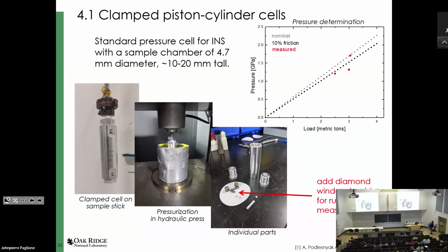But when we measured it with ruby, the first pressure point was spot on, but the second one was a lot lower. We realized it wasn't clamped sufficiently, even though we thought we were at the nominal pressure. When we clamped it again, we got to a lot higher pressure. These are caveats to be aware of, and it was really useful to have this offline pressure capability, because once you put it on the neutron beam line and you've already used 2 or 3 days of beam time just to realize your pressure was not correct, that can be non-ideal. I believe there's going to be a talk later on experiments in piston cylinder cells, so I didn't want to get too much more into those. I just wanted to point out that even with these cells, there's a lot of development and things that can be pushed.